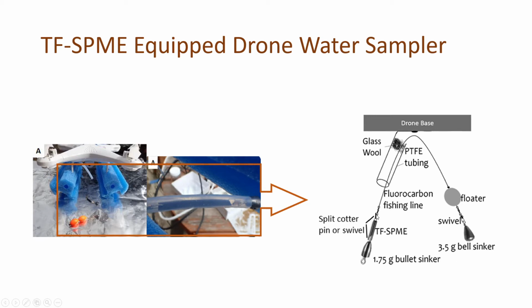To the other side of the fishing line there are two split cotter pins made of stainless steel. Between these two split cotter pins there is the thin film solid phase micro extraction membrane. To this side a lead bullet sinker was connected, and its weight was 1.75 grams. When it is lifted off for the flight, this part comes down because it is heavy, and this part goes inside the PTFE tubing, shown in the figure. The purpose of this is to protect it from environmental contamination during the flight. After it reaches the surface of the water, this part floats on the surface, and this part goes down for the sampling.